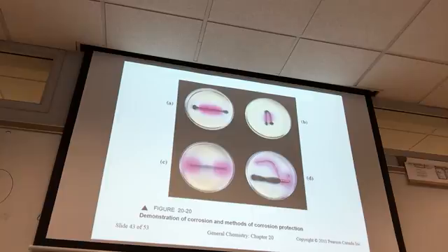If we have salt in our water, then immediately when the hydroxides are produced, the cations in the salt can stabilize that. And when we produce the cations over here, the anions in the salt can help stabilize that. So salt water will help stabilize this. Otherwise, we have to wait for the hydroxides to slowly diffuse out here to the iron tube. And so if this were pure DI water, it's going to happen slowly. In salt water, it happens much more rapidly.